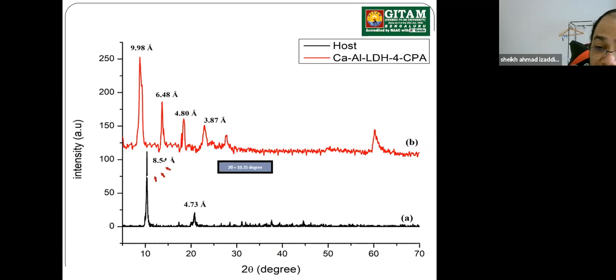Apart from that, in the interlayer as well, the amount of water molecules depends on some considerations such as the counter anions' distinctive properties, the water vapor pressure, and also its surrounding temperature. Then the basal spacing recorded at 8.54 Angstrom is actually in good agreement with the sum of the thickness of the nitrate anion, which is 4.1 Angstrom, and the brucite layer, which is 4.8 Angstrom.